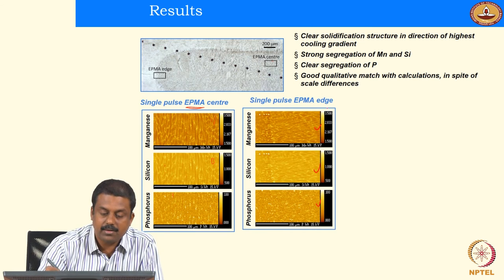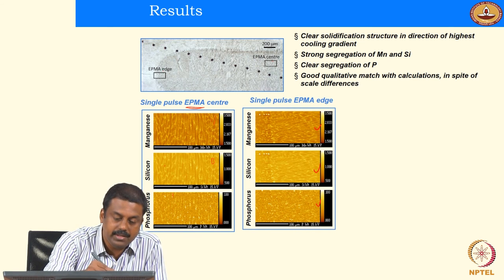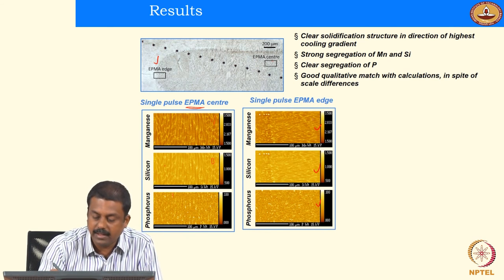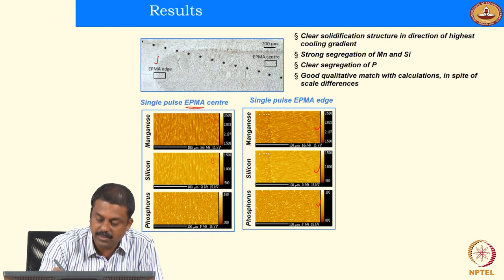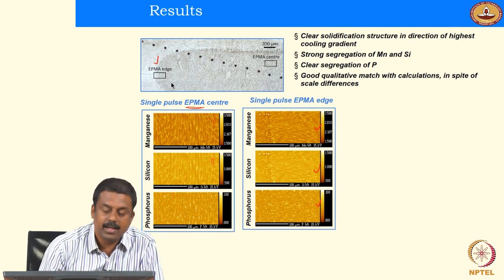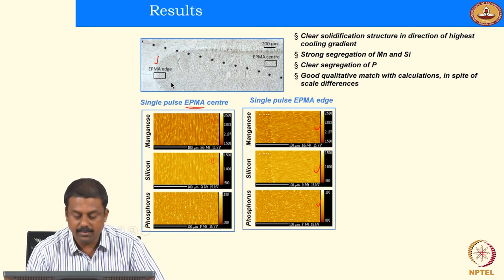And the same is actually shown at the edge region, and you also see a segregation of the manganese, silicon and phosphorus at the grain boundaries. You see the bright regions, they are all segregated regions, which are nothing but the dendritic boundaries during solidification.